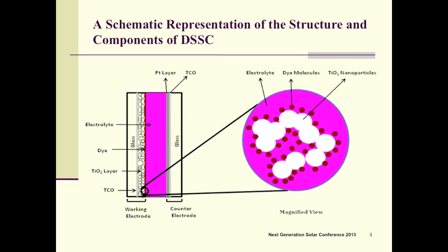The other electrode, the counter electrode, also has glass coated with a transparent conducting oxide and a catalyst layer, which is platinum in our case. Between these two electrodes we have an electrolyte which has a redox couple of triiodide ion and iodide ion, and platinum is a catalyst to reduce triiodide ion into iodide ion.